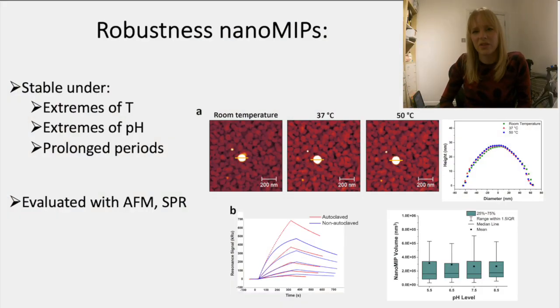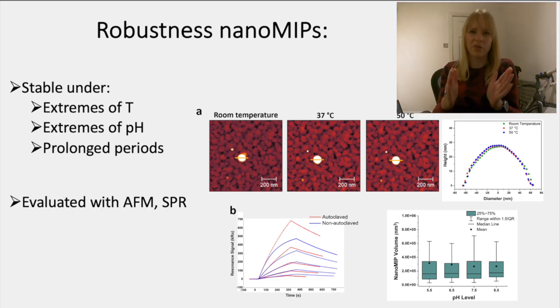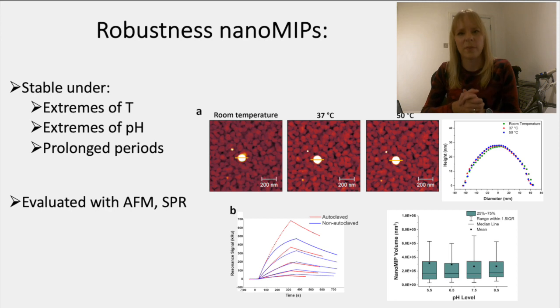Now, one of the key advantages, which I mentioned before, with these nanoparticles is not so much that, yes, we will be interested in the affinity and how good they are at binding the virus, but the robustness is very important. So what they looked at here is different conditions where antibodies would struggle. So first of all, you're able to autoclave the material. These nanoparticles come in a water-based solution. So when you autoclave it, you essentially sterilize it. You steam it, so it goes up to really high temperatures. So you could determine the affinity before and after, and could see that nothing was really changed.